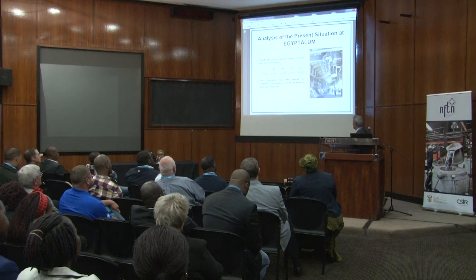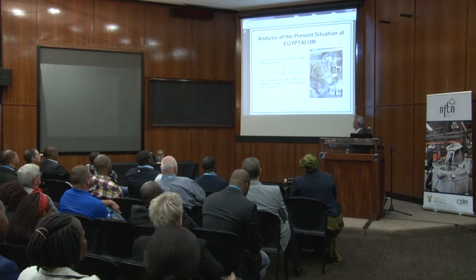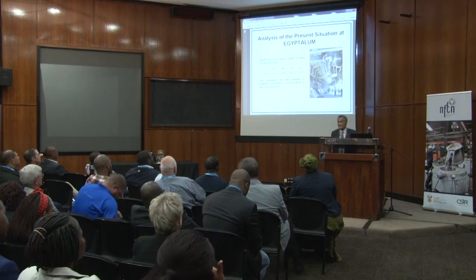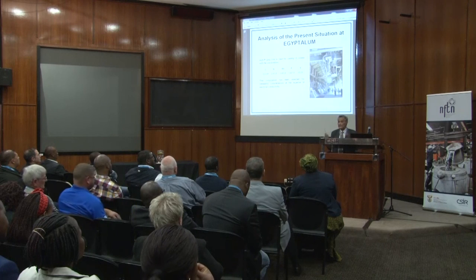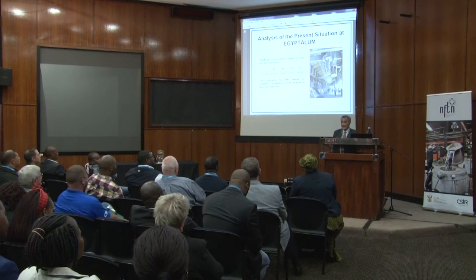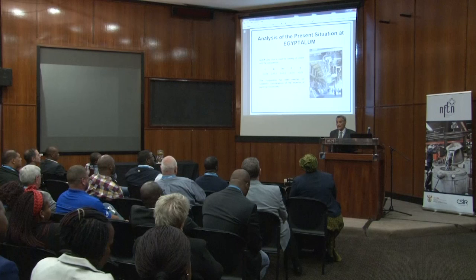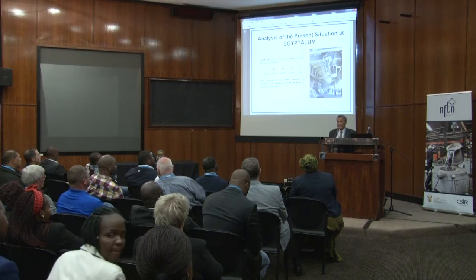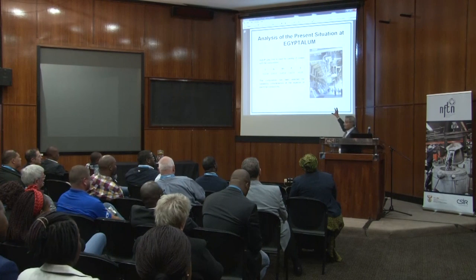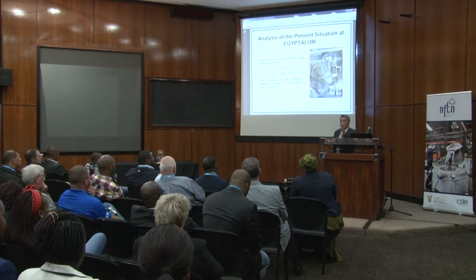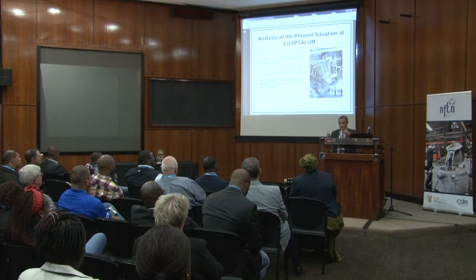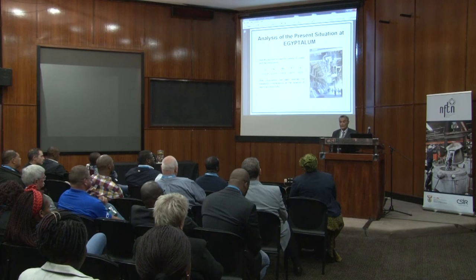And fluidity is enhanced by phosphorus addition. They used to use cast iron with 1.4, 1.5 percent phosphorus. And this really affects very much the electrical conductivity of this joint. Of the loss of electrical power happening in the whole electric cell, 50% of this loss happens at this junction. If you improve the electrical conductivity of this junction between the steel stub and the anode and the cast iron collar holding them together, then you will be saving a lot of power and a lot of money.